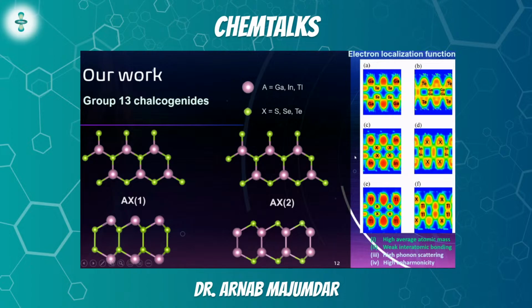Now, in an electron localization function plot, the more red it is, that means there are electrons localized in that place. And the more green or blue it is, that means that place doesn't have a lot of electrons. So if I look at D for AX2, you'll see that between the two indium atoms, it's red. That means there's a very strong covalent bond. That means the bonding is very strong. And that is exactly what we don't want. Because SLAC's second criterion was we want weak interatomic bonding.